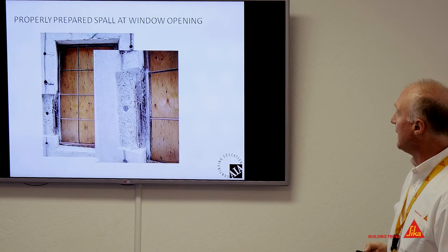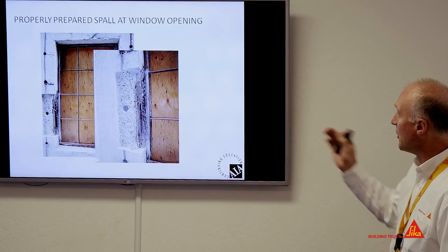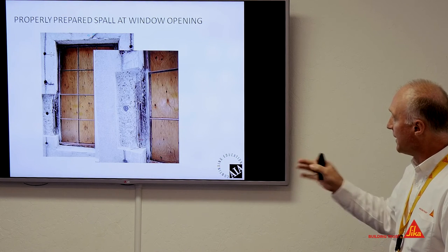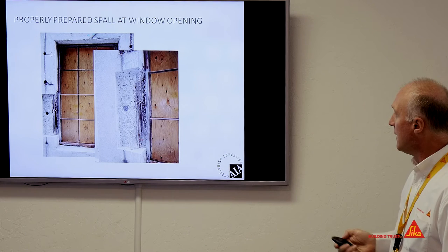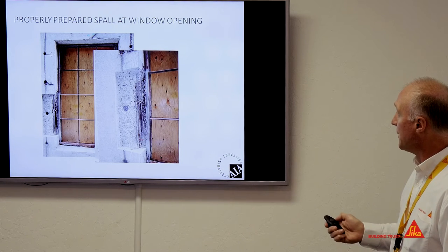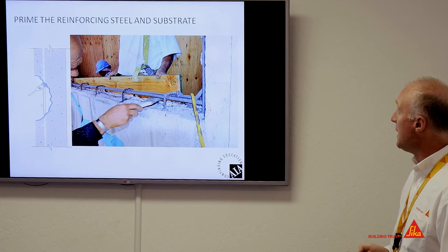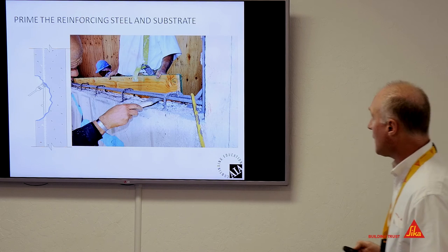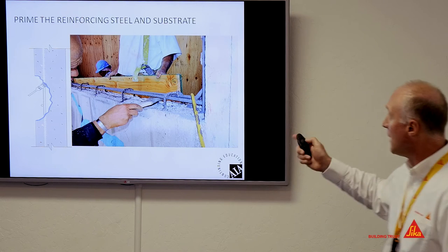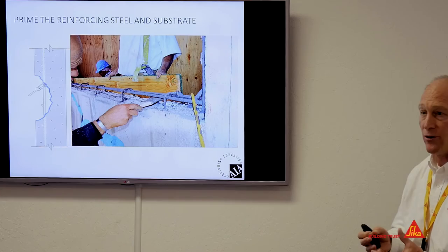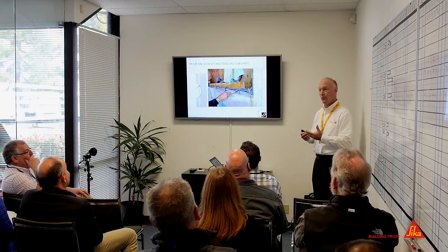Spall at a window, again, just good prep there: saw cut around the perimeter, removal and excavation of all the concrete, and then the next step would be to clean the reinforcing steel. So the key properties here: clean the steel, apply the rebar coating. We encourage this a lot, because a lot of times we're doing this because of poor cover.